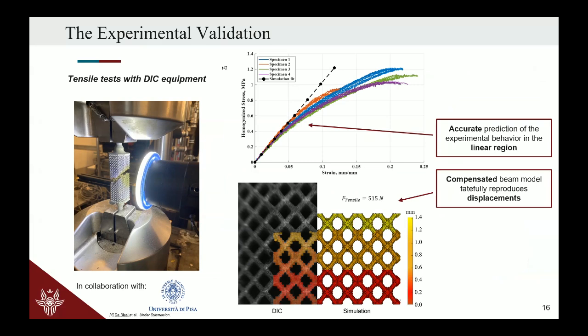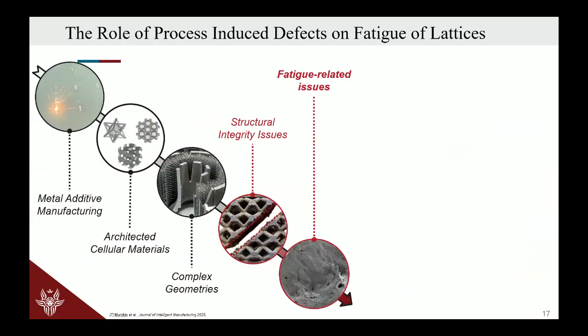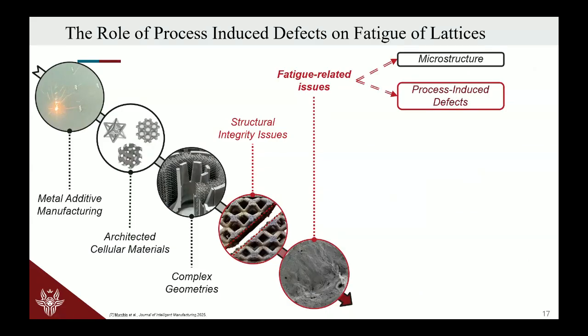if the specimens were failing where we proposed according to the numerical models, comparing the numerical results with the experimental results under static loading and now also currently under fatigue loading. So dealing with these fatigue-related issues still remains an open problem, and microstructure and process-induced defects play a fundamental role.